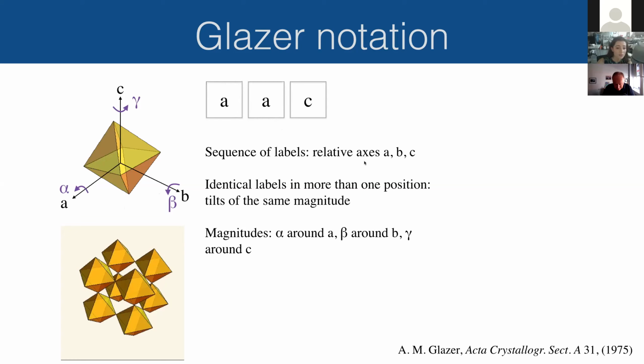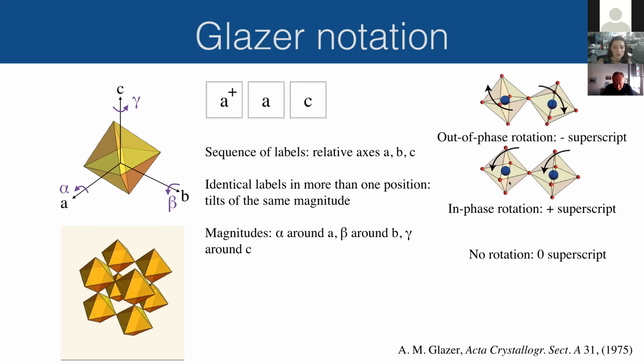And then you get some superscripts on top. So if the superscript is a plus, this means you have an in-phase rotation along that axis. So along the A axis, all of the octahedra rotate in the same direction. Similarly, if you have a minus in the superscript, it means that all the octahedra rotate out of phase, so they're alternating one way and the other. So in this case, you have in-phase rotations and out-of-phase rotations, but they have the same magnitude in this example. And if you have a 0 in the superscript, it's a bit redundant, but it just means that there is no rotation or tilt around that axis. And what you do is you use the Greek letters alpha, beta, gamma to quantify the tilt. So you would say, in this case, for example, gamma is 0 degrees.